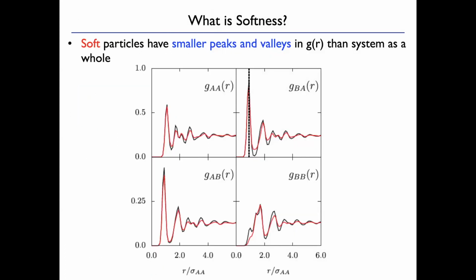Okay, so what is softness? As I told you, it is a weighted integral of the local g(r). But I can just look at soft particles and look at their average pair correlation function. That's the red, and I can compare it to the pair correlation on average. This is for a mixture of two size particles, A and B. What you see is that the red and the black, the soft particles and all of the particles, have very similar pair correlation functions, but the softer ones do have lower peaks and higher valleys. And what that means, and this comes back to the old idea of a cage, is that a particle in a glassy system has to escape from a cage of its neighbors. This is a way of quantifying the cage. So softness gives you that.